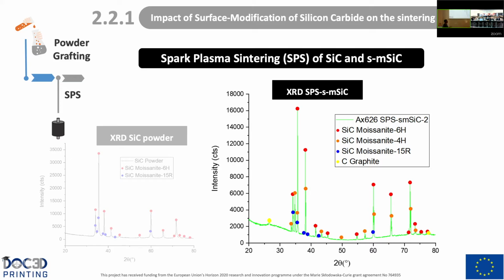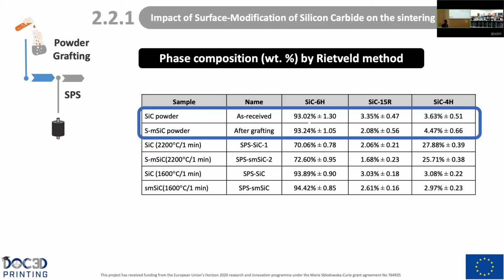If we compare with the surface modified silicon carbide after spark plasma sintering, again 6H, 15R raw material, like powder as received, graphite due to contamination, but again 4H states. So actually we have similar material physics effects in both materials. So regarding the phase composition, again by Rietveld method, here we observe similarities with the silicon carbide powder and surface modified silicon carbide powder. And effectively, for the silicon carbide and surface modified silicon carbide after the spark plasma sintering, we